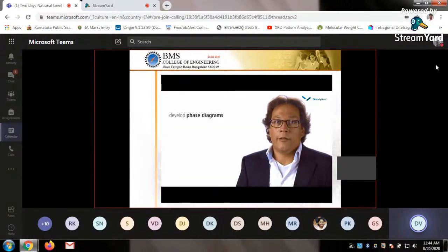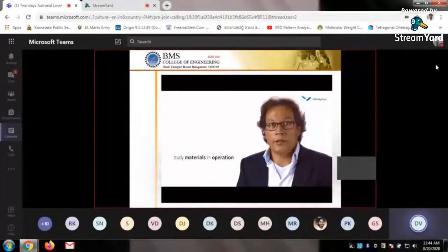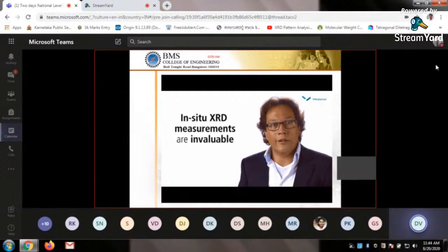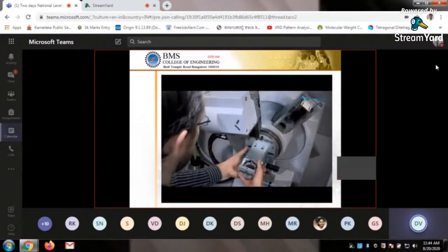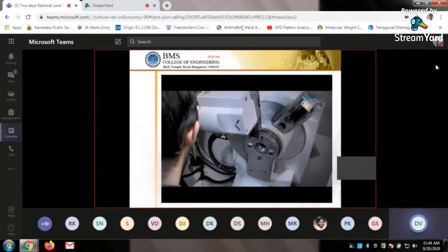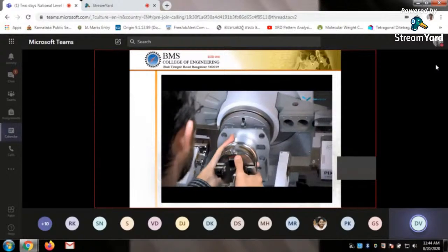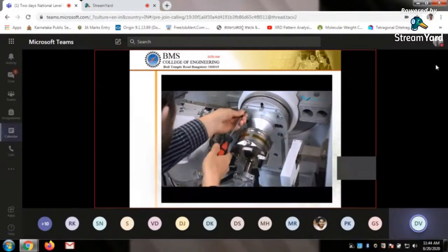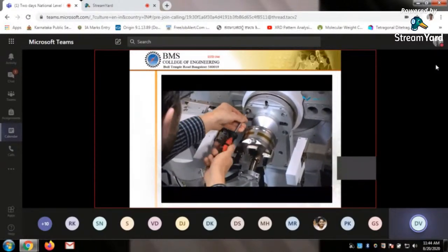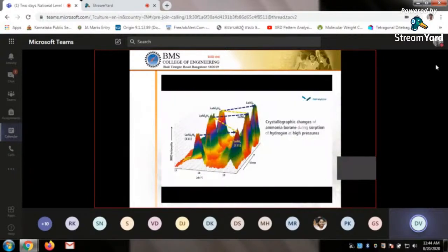When you want to develop phase diagrams, optimize process parameters, or study your materials in operation, in situ X-ray diffraction measurements are an invaluable tool. X'Pert3 Powder diffractometer supports a number of sample stages with automated control of sample environment, such as variable temperature, humidity, strain, and pressure. The example shown here reveals the crystallographic changes of ammonia borane during the sorption of hydrogen